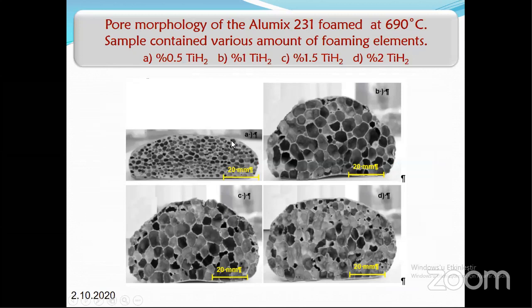Experimental result. This is some morphology of the Alumix 231 foam at 690. Samples contain various amounts of foaming elements: 0.5% titanium hydride, 1%, 1.5%, and 2%. So 0.5% gives a small porous structure, 1% is coarse with thin wall thickness. When you go further, density is decreasing, but the mechanical properties also decrease.